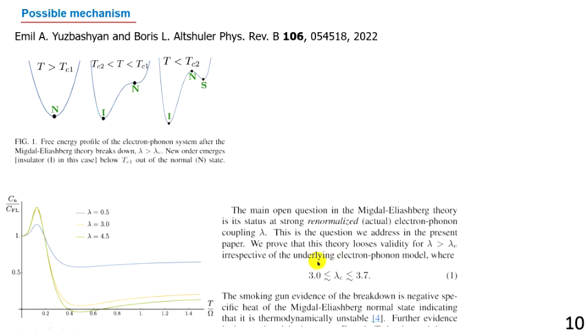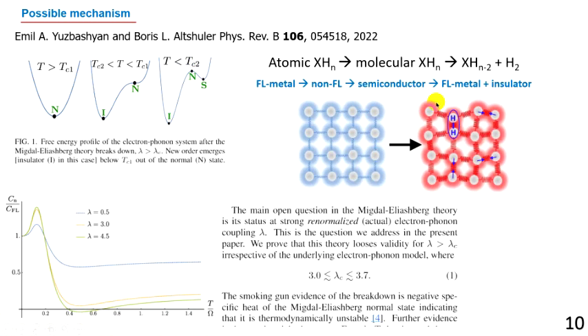They found that if this parameter of electron-phonon interaction is over some critical value, the heat capacity of superconducting materials will be negative, and the superconducting state in this case will not be stable and will turn to insulating state. It's something we observed in hydrides. When we decrease the pressure, we usually go to molecular polyhydride. It may be semiconductor or strange metal, and after that, this molecular polyhydride decomposes with formation of two separate phases. The first is again the metallic and maybe even superconducting phase, but with lower hydrogen content, and the second phase is insulator. It's a molecular hydrogen.